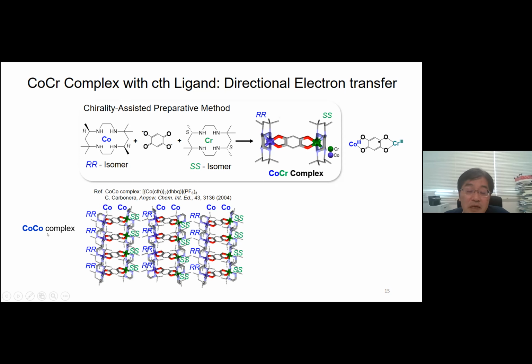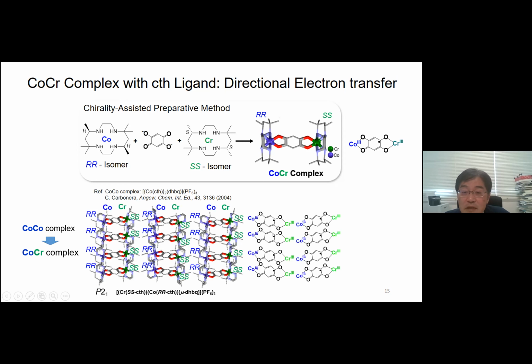And now we exchange this cobalt side with chromium. This is exchange from cobalt to chromium. So this means this cobalt side is changed to chromium. This means molecules are oriented in the same direction in the crystal. So if these molecules exhibit electron transfer, then it is directional, always from center to left. So we investigate this charge transfer property and polarization switching property.